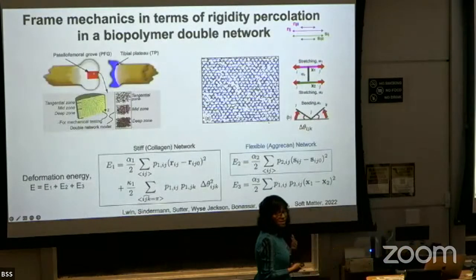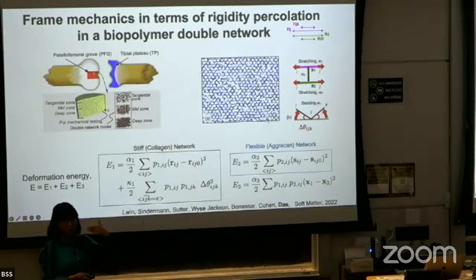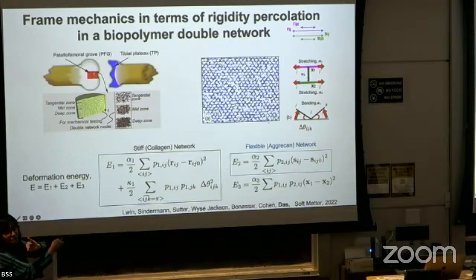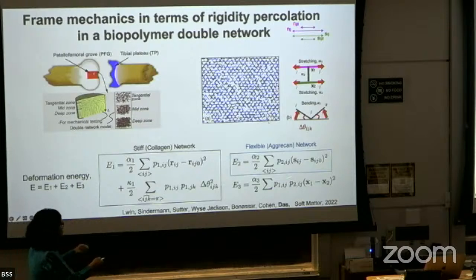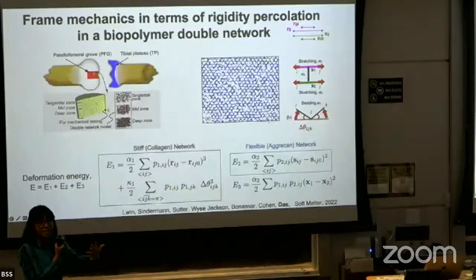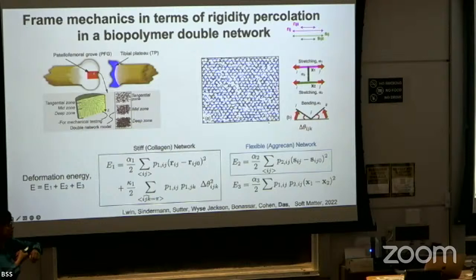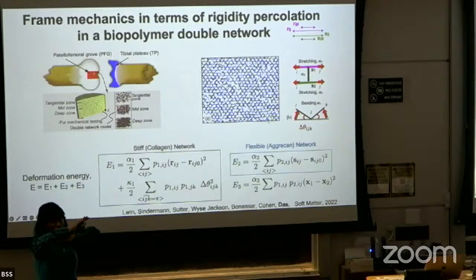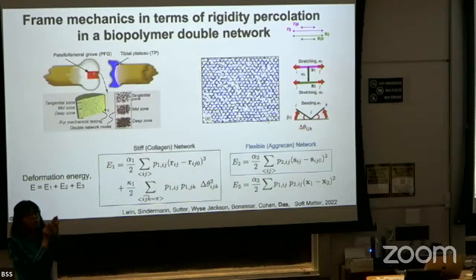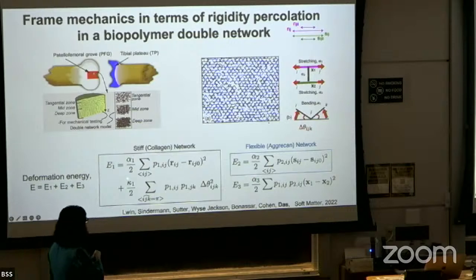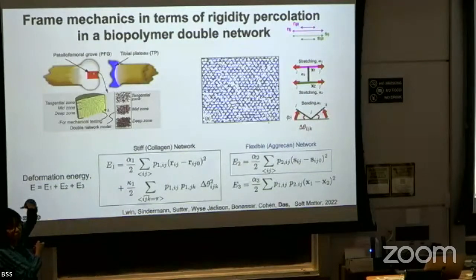We thought the simplest way to model it is the next iteration that Marcus's question helped us think of. Instead of having a background gel, we say that we have a collagen network, which is coupled to an aggrecan network, a second network. But the second network is a flexible network, so there is no energy cost of bending the fibers in the second network. The two networks interact with each other at the midpoints of bonds, not at the nodes, connected by weak Hookean springs, only when bonds in both networks are present. This is the simplest mental picture, or cartoon model picture, of a composite network, essentially a double network.